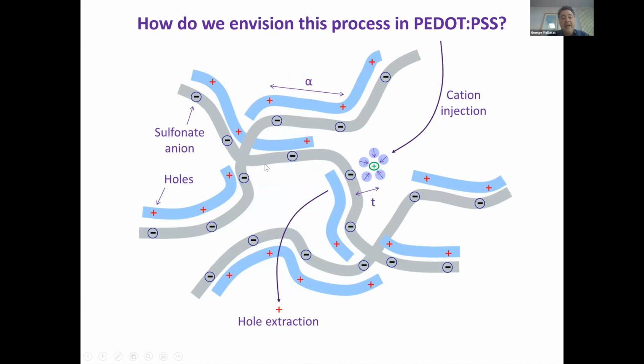Now, in a three-dimensional electrode like PEDOT:PSS, you come up with the following model. You have PSS chains that carry the sulfonate ions, shown here. Along the PSS chains, we have the PEDOT chains that are polymerized side by side and would have the holes that are obviously free to move and jump from one chain to the other, giving rise to macroscopic conductivity. Then what happens if you inject a cation from the electrolyte? It will come and compensate the sulfonate anion, while a hole from the adjacent PEDOT chain that was compensating this anion would be extracted through a metal electrode to give you charge neutrality.